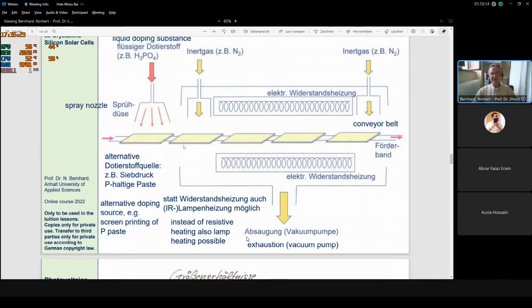The advantage of this process is that it's inline, that means a continuous process. That means every wafer sees precisely the same process, whereas in the previous process, we might have a certain position dependence in the boat or something else. A disadvantage is, whereas the previous one is a fully sealed furnace, here we have just a separation from the outside by this inert gas curtain, and therefore, of course, the contaminants in this process are higher than in the previous process. Basically, this is a cheaper process for non-leading edge technology, whereas the previous one was a more expensive process for leading edge technology.